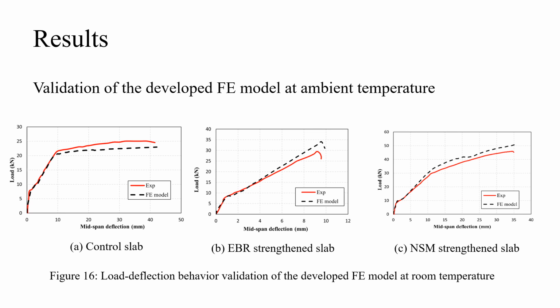There's a quite overprediction of the ultimate load value in both strengthened slabs, the EBR and NSM. So this minimal difference can be attributed to the variation in material properties between the experimentally tested values and the values assigned to the model. So the finite element model confirms the superiority of the NSM technique in terms of higher ultimate loads and deformational capacity, as can be seen in Figure 16C.